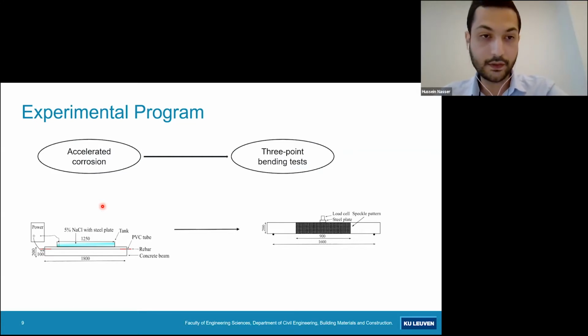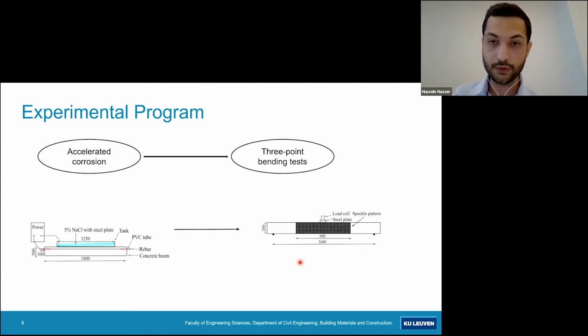After the target corrosion level was reached, the beams were subjected to a 3-point bending test as shown in the setup to the right. During this bending test, the load was recorded using a load cell, while the deflections were recorded at midspan using LVDTs. Additionally, I applied the speckle pattern around the midspan so that I can monitor the evolution of cracks using digital image correlation. This way I can obtain full load deflection curves, and I can also have an idea about the evolution of bending cracks.